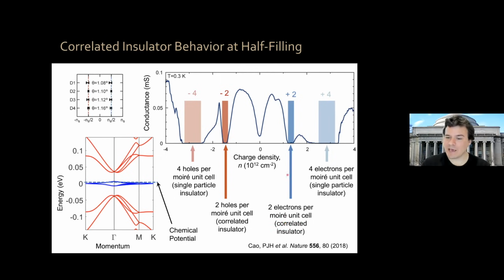Now, this type of behavior where you have these correlated insulator states only happens in a relatively narrow angular range around these 1.1 degrees, okay? We have measured, by now, dozens and dozens of devices. Only when your twist angle between your structures is between 1 and 1.2 degrees, more or less, that's the margin, 1.1 plus or minus 0.1 degrees, do you have this correlated insulator behavior. So it's very tightly coupled, intimately connected to these flat bands that occur at the magic angle.